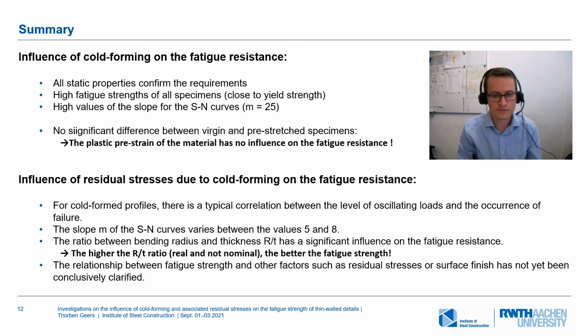The curved test specimens also show a clear relationship between the level of the alternating load and the occurrence of failure. The slope of all SN curves is between 5 and 8. It could be shown that the R/T ratio has a decisive influence on the fatigue strength. The quantitative influence of the residual stresses on the fatigue strength still has to be assessed.